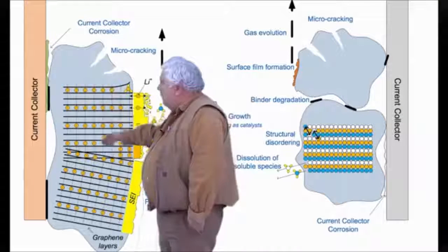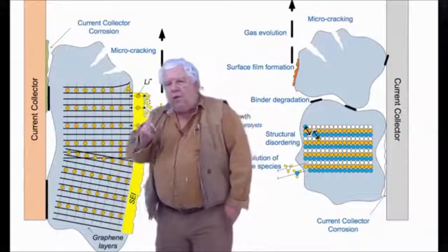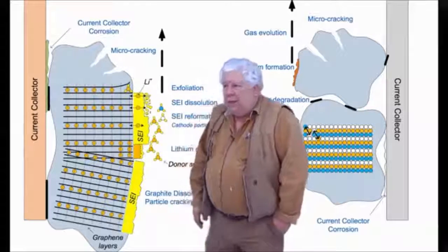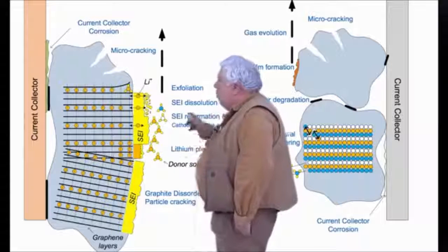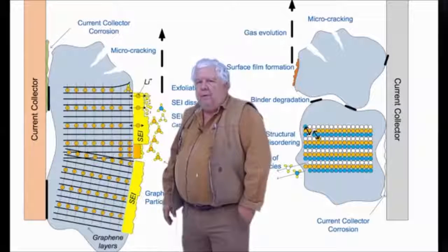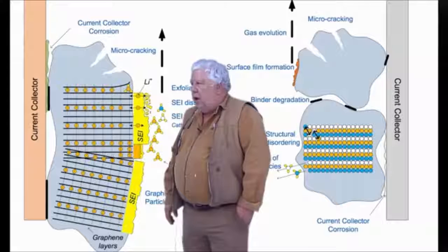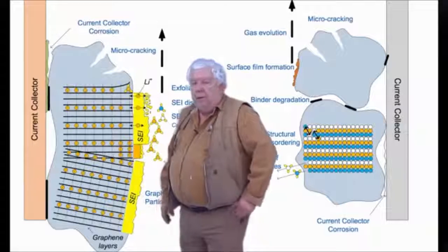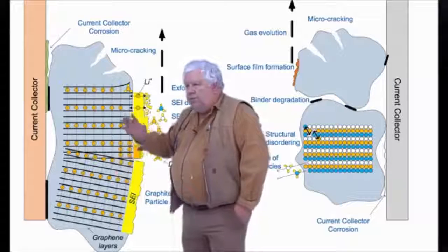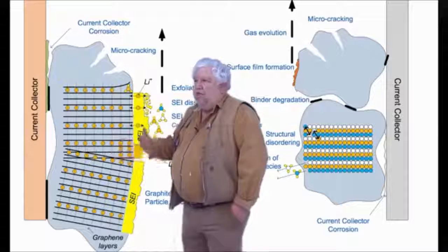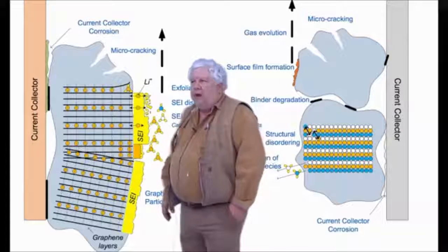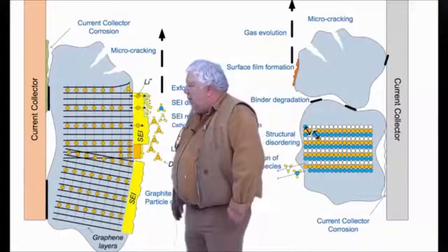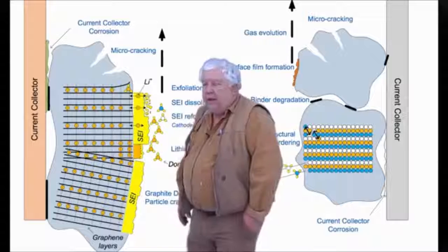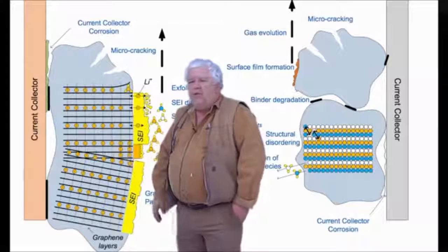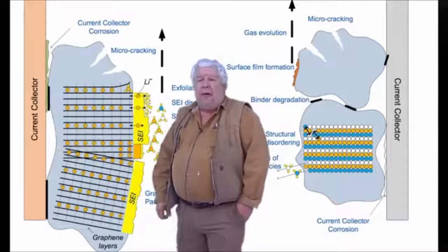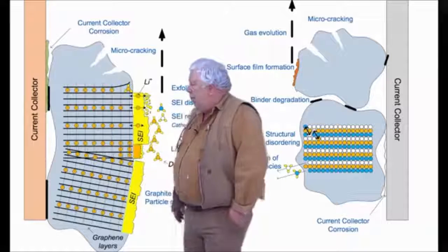Now, before that even happens, at about 90 degrees centigrade, one of our organic solvents, dimethyl carbonate, I believe, DMC, has a boiling point of 90 degrees centigrade. And that starts to give off gas, which causes our cell to swell up. And there is no scenario where a cell simply swells on its own. There's no magic here. Swelling is telling, it's damage. And it's caused by the gasification, usually, of DMC. And DMC also gives it kind of that sweet pear smell when it vents. And you can smell a battery going bad. It's kind of a sweet pear smell.